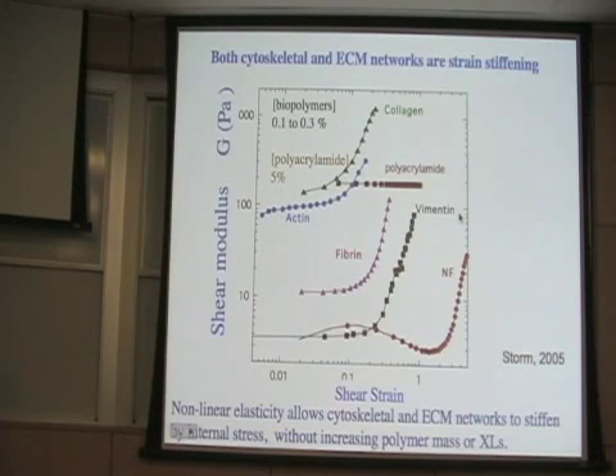And one of the things that's now fairly commonly seen is that if you look at the most simple nonlinear behavior of materials that are characteristic of the stuff inside the cytoskeleton and out in the extracellular matrix. So collagen, cross-linked actin, fibrin, which I just showed you, intermediate filaments like vimentin or neurofilaments. So both the extracellular polymers, collagen and fibrin, the intracellular polymers, intermediate filaments and actin, they all have this characteristic that their shear modulus is a very strong function of the strain. They are very soft and compliant at low strains, and what is low for these things depends on their own stiffness and their cross-link density. But low strain typically is a few percent or maybe 10%. But as you increase the strain, the materials stiffen, and they stiffen a lot. They stiffen orders of magnitude. And this is a reversible process.